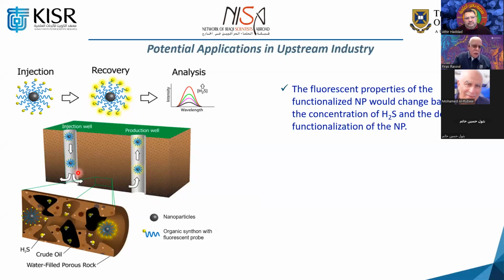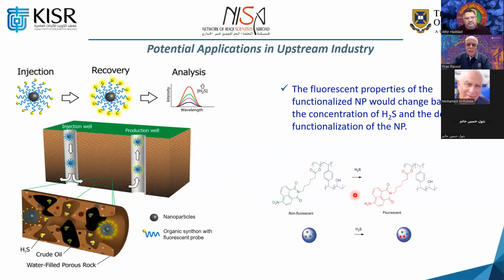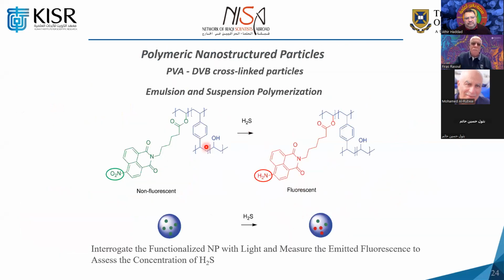You will be able to inject your functionalized nanoparticles into the injection well and collect them from the other side after they react, and then you will be able to analyze how much H2S has been there. What is the level of H2S? You will be able to quantify it by using fluorescence spectroscopy in our case, and this is what I'm going to show you: how we synthesize these materials.